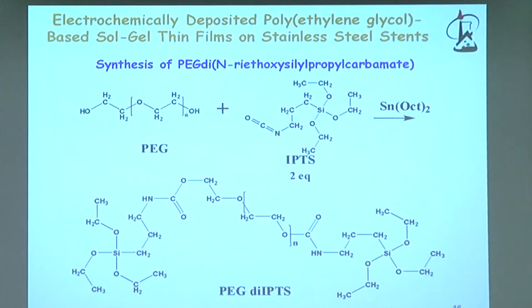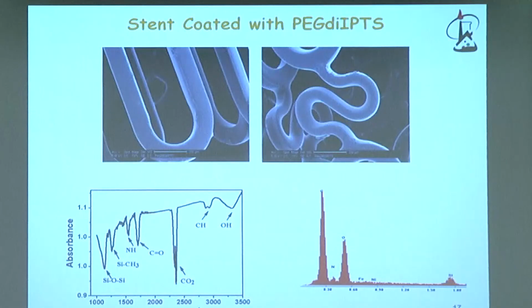What did we do here, or how did we use the fact that we can deposit sol-gel? So we synthesized this dimer, as you can see here. This part of the silica, you can see here, is a silicon-carbon bond, and here you can recognize polyethylene glycol. Polyethylene glycol is a polymer which is very hydrophilic, and because of that, it prevents the formation or the adsorption of proteins, bacteria, and so on. So we coated the stent electrochemically. Here is the cell of the stent. You can hardly see that it's actually coated. And here you can see we have very good evidence that indeed the coating is there.